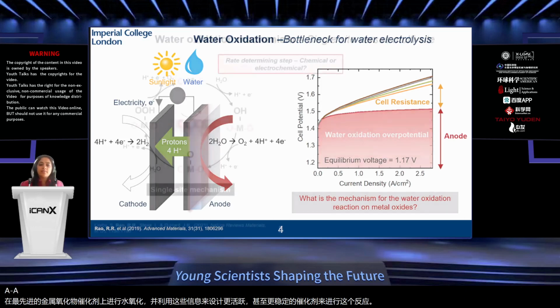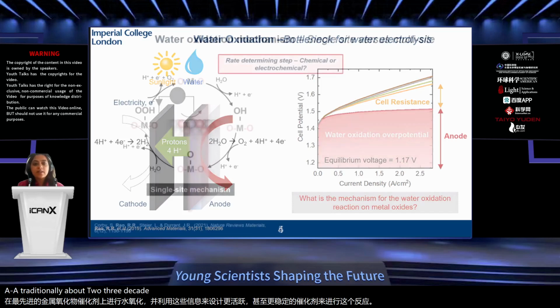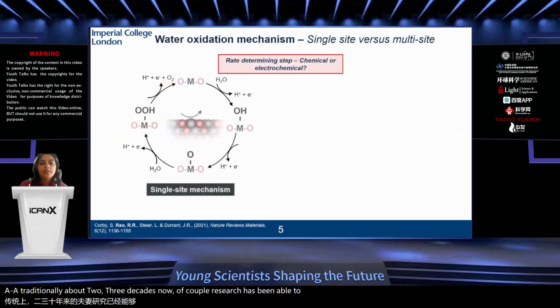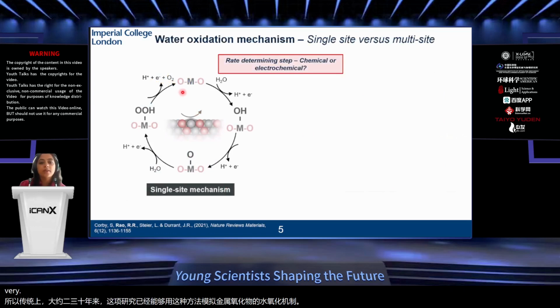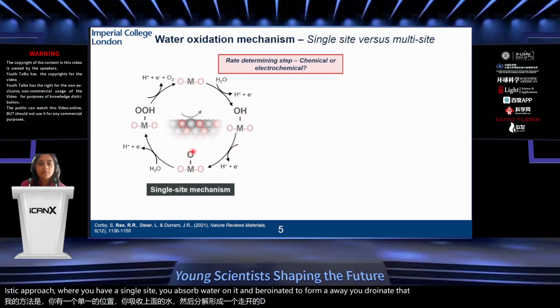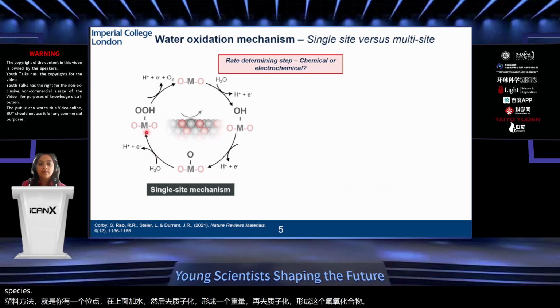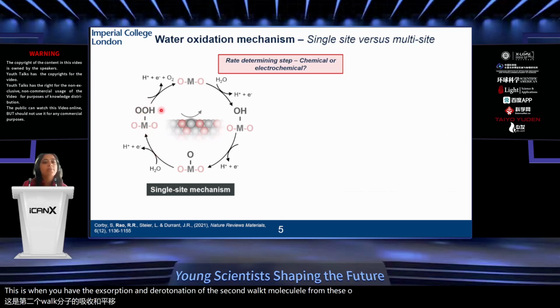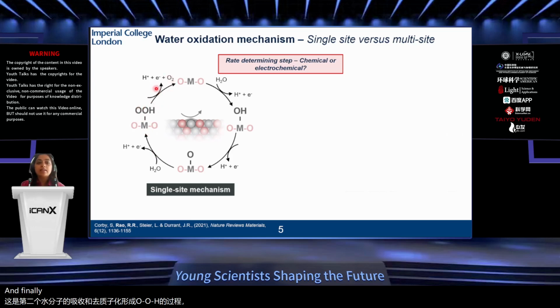So traditionally, about 2 or 3 decades now of catalyst research has been able to model the water oxidation mechanism on metal oxides using this very simplistic approach where you have a single site. You adsorb water on it and deprotonate it to form OH. You deprotonate that again to form this oxo species. This is when you have the adsorption and deprotonation of a second water molecule to form these OOH species. And finally, the last deprotonation step results in the evolution of oxygen. So this is a very simple single site kind of mechanism.